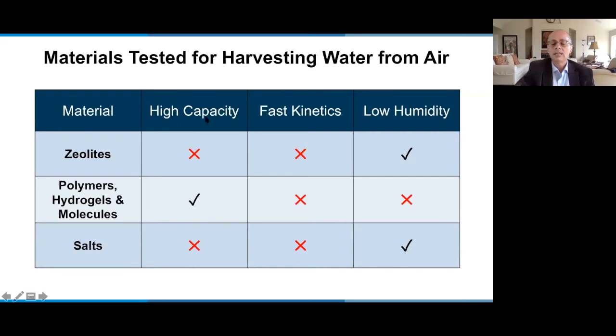One is that your material needs to have high capacity. If it doesn't have high capacity, then you have to cycle a lot. And if you cycle a lot, you need more energy. You also need fast kinetics. If the water goes into the pores and it's stuck in the pores and you can't get it out, or you can get it out but it's very slow, then you're not going to get enough water out. So you need fast kinetics, and you need this material to be able to operate below 50% relative humidity, in those regions, as I showed you, where you have few grams of water in the atmosphere per cubic meter.